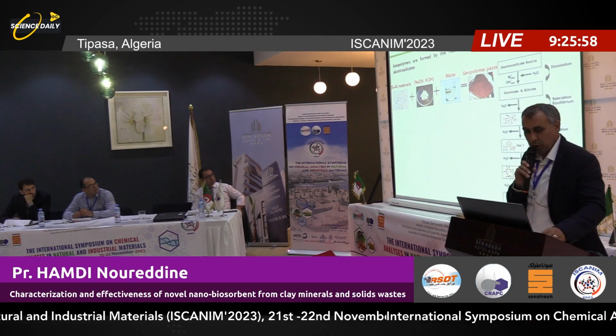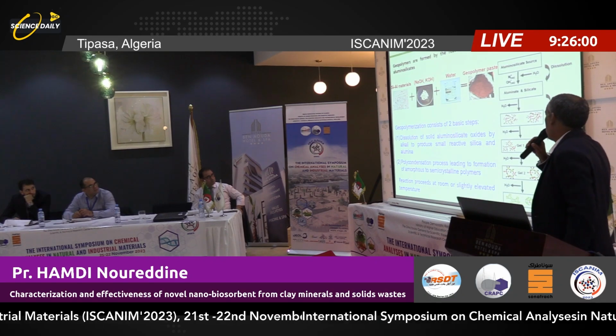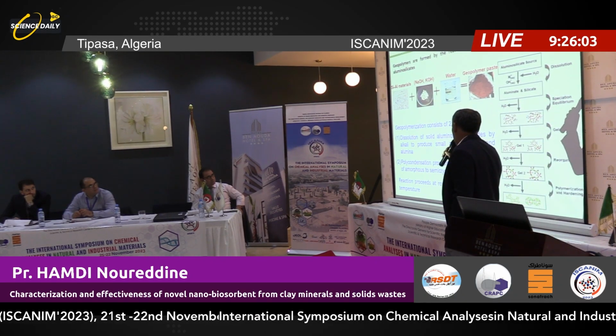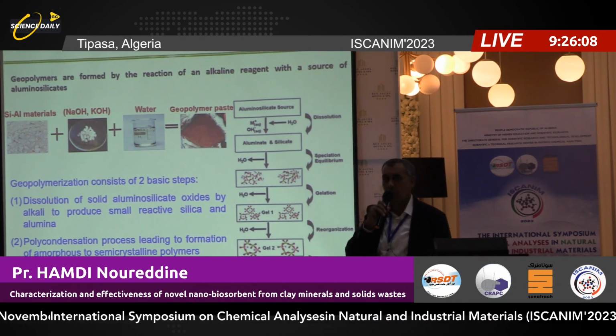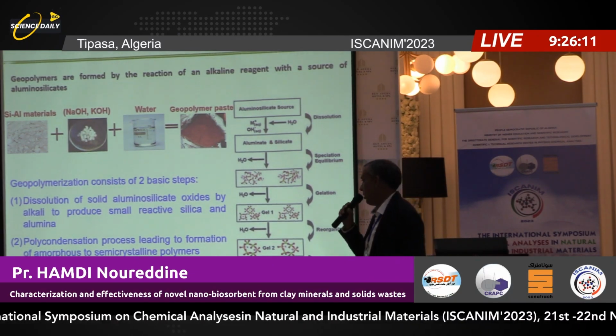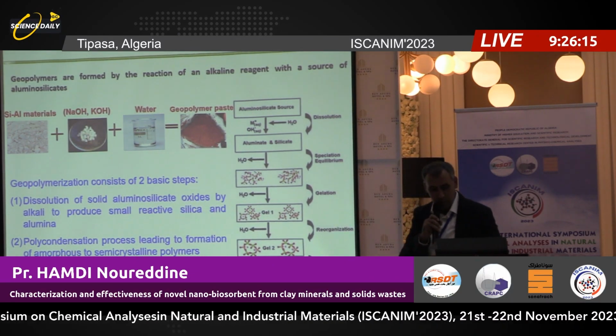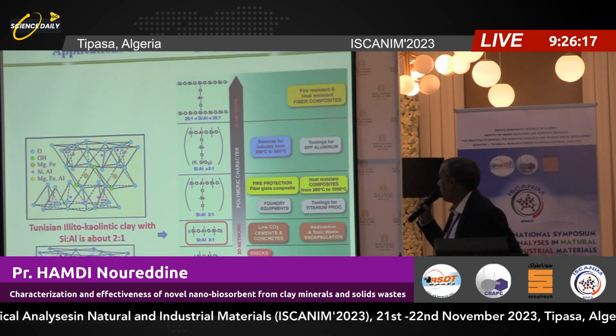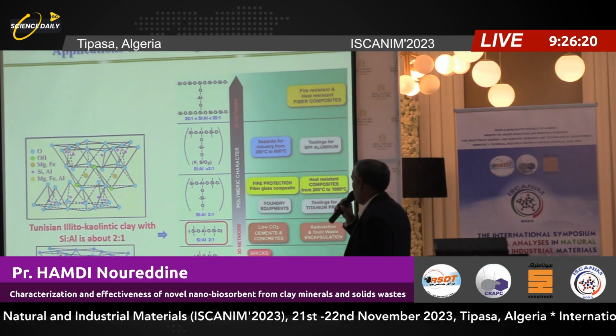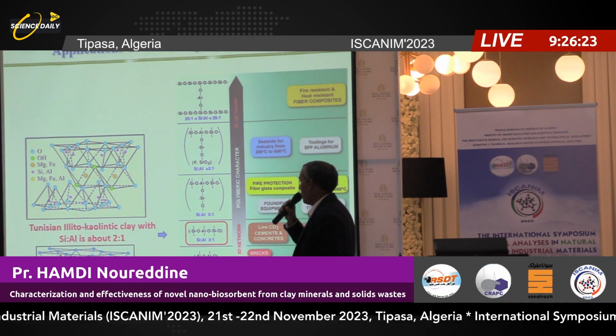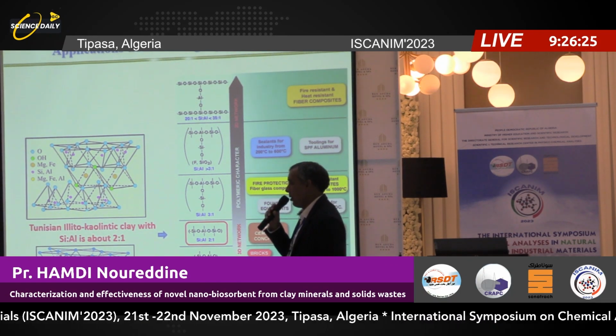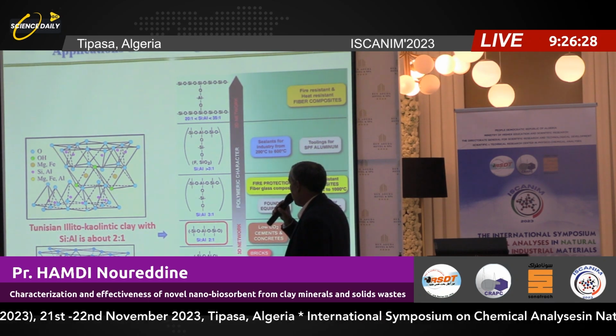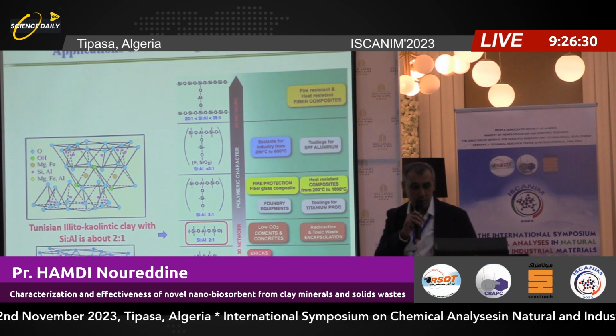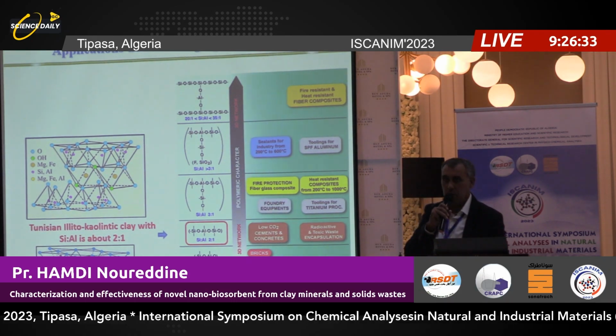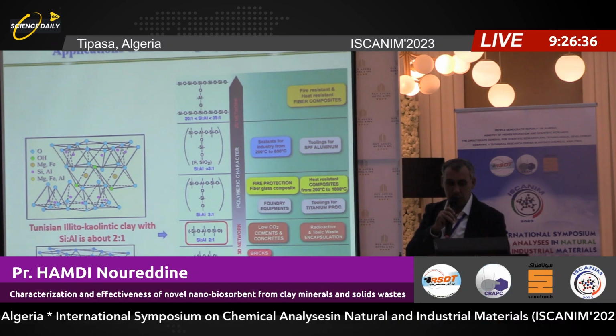In general, we have two stages for the geopolymerization. The first one is the dissolution of the aluminosilicate. The second one is the polycondensation, and this reaction can happen at room temperature or at high temperature. In our study, we used a silicon to aluminum ratio of about 2 because we have illito-kaolinitic clay from Tunisia, and the application can be for the environment, in general the treatment of water and wastewater.